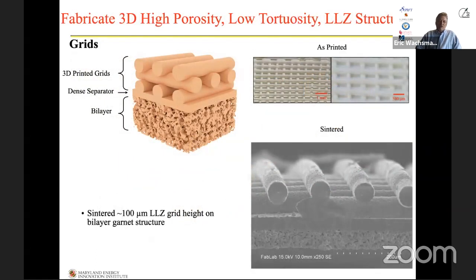We made a number of different structures, and this is one of them. This is a grid structure. What we've done is make that bilayer. If you remember, I showed that to you before. That's on the bottom of the cell. That's what we're typically using for putting lithium metal in, and then we put the cathode material in the grids. Again, these are just grids back and forth. You can see the as-printed photographs on top and the sintered structures below. We can make these on the order of about 100 microns high of this lithium, lanthanum, zirconium, garnet type material.